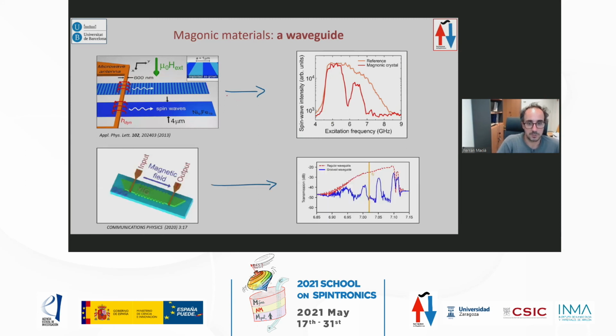In the first one, what happens is that in two strip lines, one without anything, nickel iron, so this is permalloy, and another one with the same material but with some ion implanting to reduce the magnetization, you can see that the orange one is the reference, and in the other one you created some gaps. This is not a fortunate color, but you create some gaps that forbid certain frequency propagation.